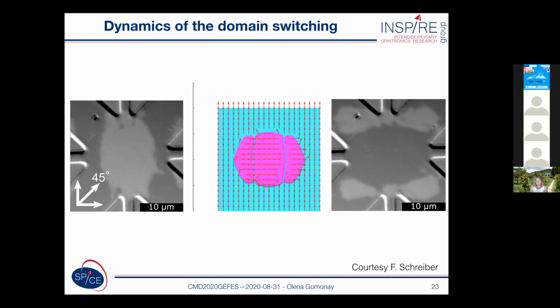In the simulation, we also see 180 degree domain walls seen as thin blue lines in the pink region. We do not see these lines in the experiment, but we can attribute these 180 degree domain walls to the boundary conditions used in the simulations.